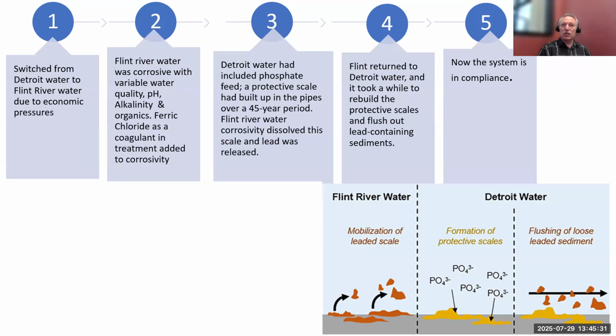Now remember, in the previous slide we looked at the chloride to sulfate mass ratio. So the water was already corrosive, and then this additional ferric chloride added more chloride on top of that CSMR when you look at it from that perspective. So that added to the corrosivity. Now before that, there was 45 years of this Detroit water flowing through the pipes, and Detroit water had a phosphate feed. So inside these pipes, there's a 45-year buildup of scale inside the Flint water pipes where the lead was captured in the scale. And so the corrosivity of the new water coming in caused this scale containing lead to be released.